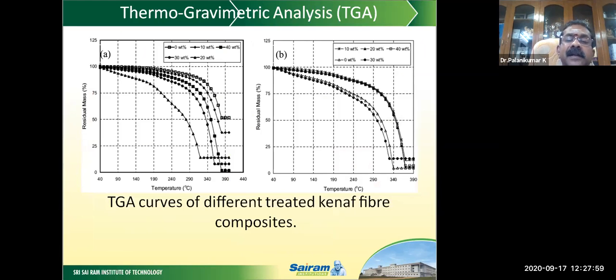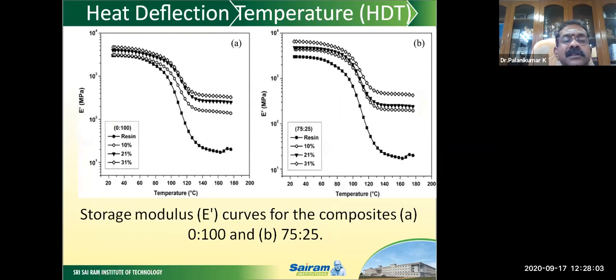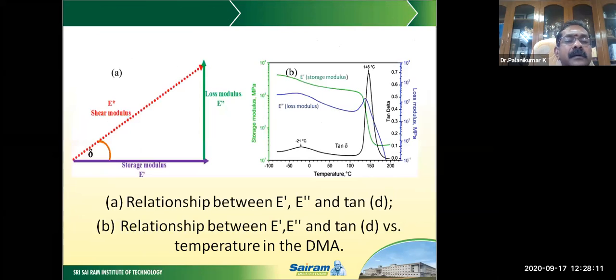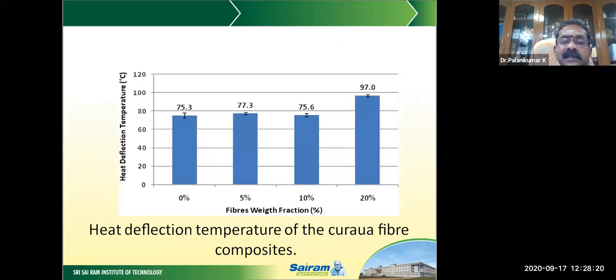So this is a TGA curve of different treated kenaf fiber composites. This is the storage modulus observed for the composites when increasing the temperature. So the relationship between E dash and tan delta for the DMA analysis. Heat deflection temperature of the kenaf fiber composite. So when we see the heat deflection as the fiber weight fraction is increased to 0%, 5%, 10% and 20%, when compared to 10%, 5% plays an important role. But when you increase the percentage of fiber, then we have a heat deflection temperature of approximately 97 degrees centigrade.